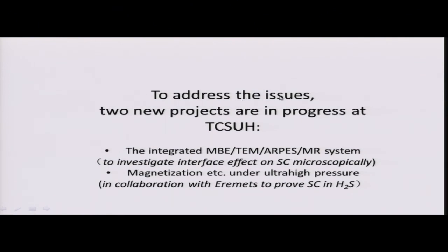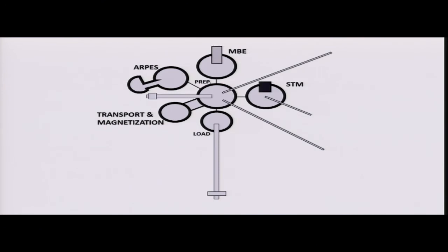The other thing is to address this issue. One is, as I mentioned, interfacial superconductivity, and the other is whether the recent announcement is really a superconducting transition. On those things, we are doing two experiments. Essentially, we look at the interfacial effect microscopically. You grow the material in the MBE chamber in situ, and then you continue to take it out to do STM microscopic measurements, and then later on do macroscopic measurements. This is an integrated system that we're building at this moment.